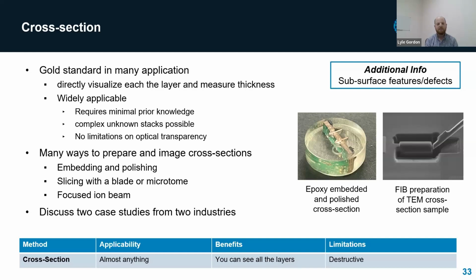For soft materials, often you can use something even as simple as a razor blade in the lab to make a decent cross section, or for certain materials, a microtome will work better. And so these apply to almost anything, but of course your sample is destroyed, you cut it in half. And the benefit is you can see all the layers in the sample in the region you're interested in, and you get direct pictures. So you don't need to know anything, there's no modeling, and you can just directly measure the thickness of all the layers, and you'll be able to see variation.